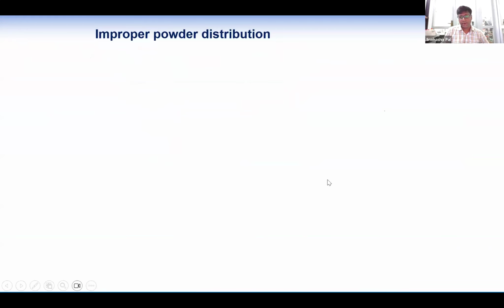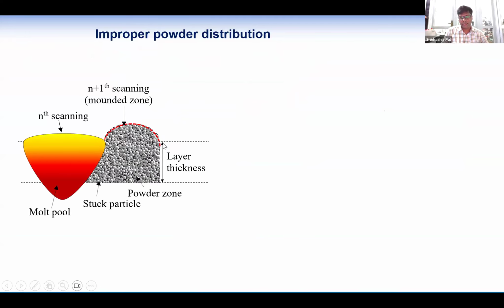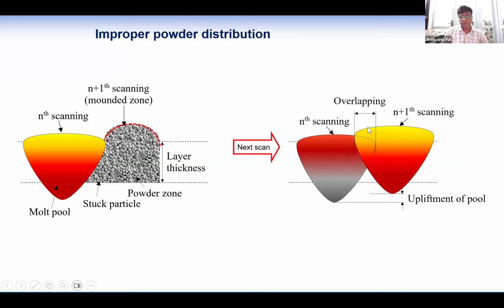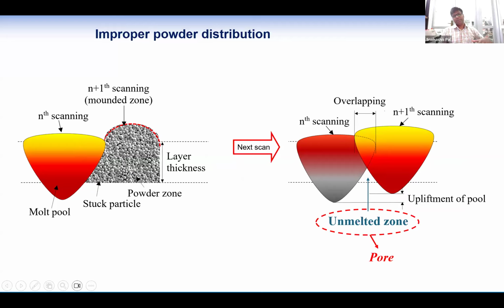So that's the problem. And also, let's say, improper melt pool. Improper melt pool mostly occurs due to improper powder distribution. That is, somewhere the powder can be in excess, or somewhere there can be less powder. If there is excess powder, the melt pool will be a little bit higher, so there is a higher chance of more gap in the bottom place, and maybe an unmelted zone. If there is less powder, then the melt pool will be in the lower portion, or a lot of powder particles will be sputtered out due to the high energy density occurring there. So there will be porosity again.